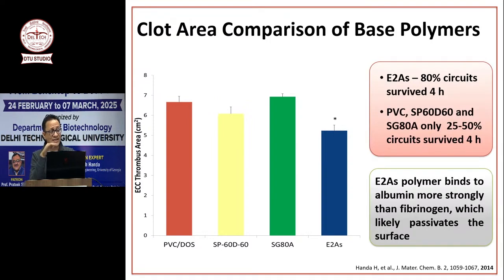Plus, 80% of the circuits survived in E2AS, whereas only 25 to 50% of circuits survived 4 hours. Meaning, I also told you yesterday, one of the things we do with this circuit is we measure the flow rate over a 4-hour period, right? So we measure flow rate, we count platelets every hour, we look at the clot formation in the end, and we also do aggregometry every hour to make sure that platelets are aggregating.